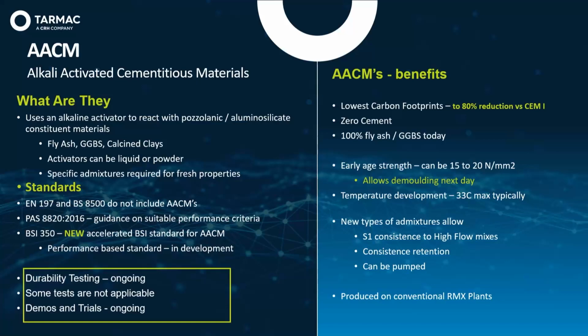Tarmac, however, have adopted Wagner's blended alkali activator in liquid form, which disperses much more easily and readily through the mix. And combined with specific admixtures, they have also successfully developed a mix that incorporates up to 70% of PFA. That particular solution has been seen to deal with the low strength gains and also managed to remove that powdery latence effect that you tend to see with GGBS mixes.